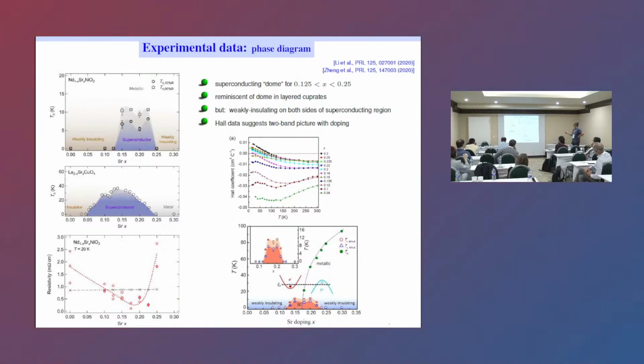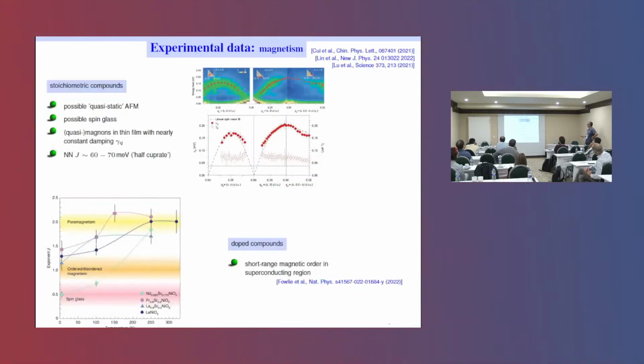And even more strikingly, in the low doping, underdoped region, it's still super weakly insulating, and there's no metallic or metallic-like transport yet found. This could be true sample issues, but even with the new samples, this still holds. As you can see, there's not much conductivity there. So this goes back to this doping aspect, that putting holes into this nickelate might be quite different, might be much harder than compared to cuprates. And the Hall data was already discussed by the previous speakers.